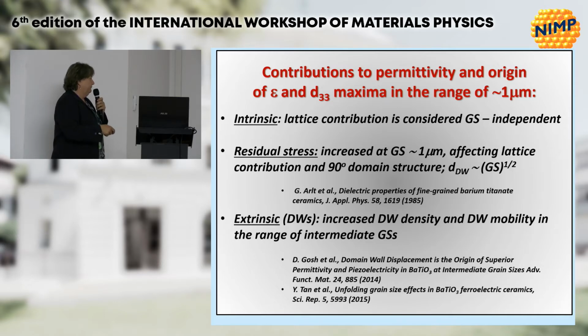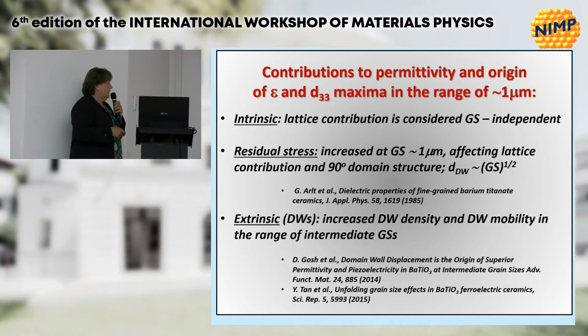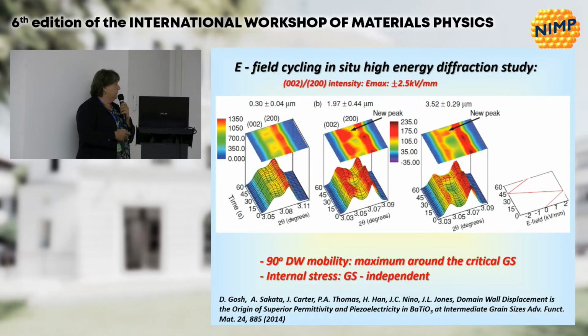Like 5 or 6 years ago, these two studies concluded, for example this study from the group of Jacob Jones, that domain wall displacement is the origin of superior permittivity and piezoelectricity. So no other effects, but the role of domain walls. And this somehow was confirmed also by this last paper on the topic of TAN.